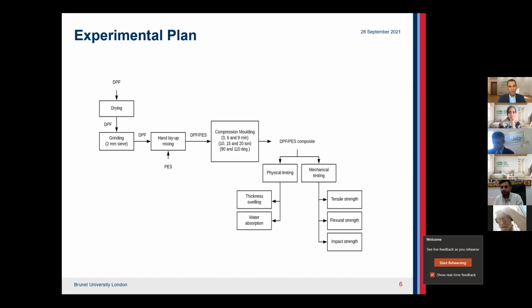So after developing the composites, in order to evaluate the processing parameters effect, 2 types of testing, both mechanical and physical, were done. For the mechanical, the tensile strength, flexural strength, and the impact strength were evaluated. And for the physical testing, the thickness swelling and water absorption were evaluated.